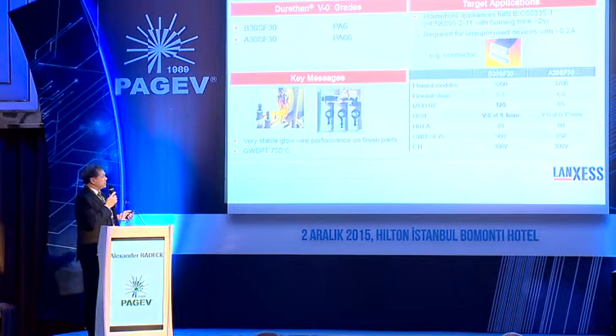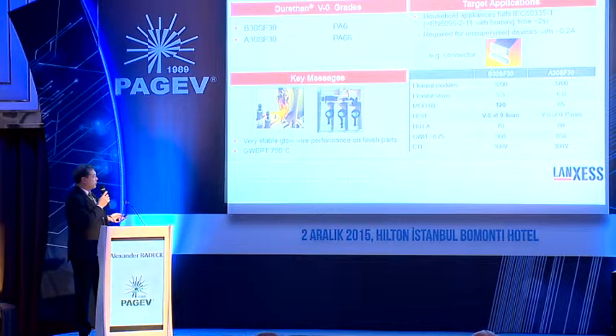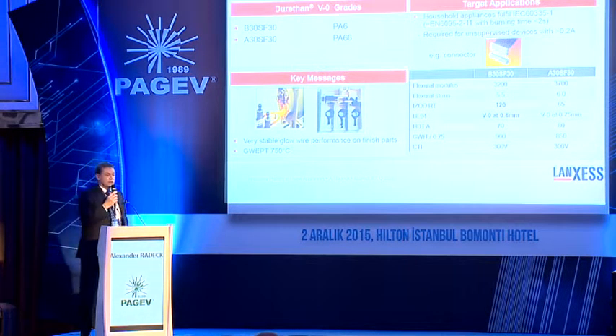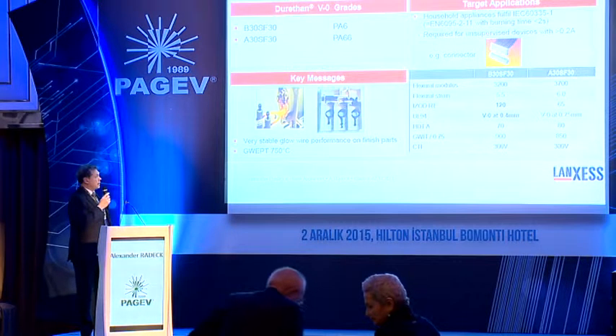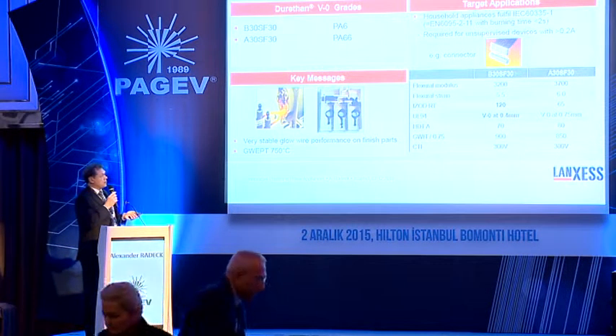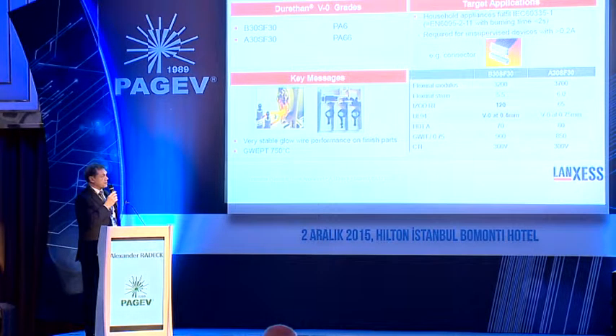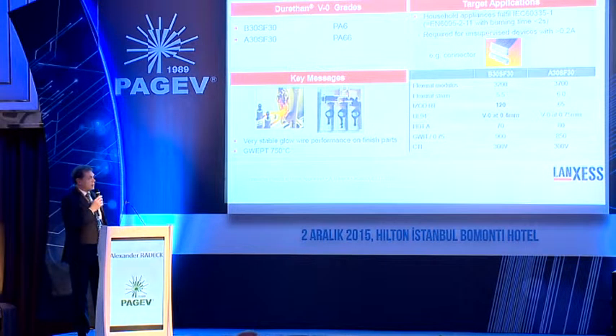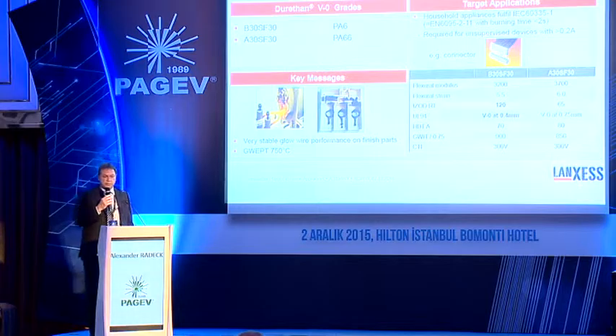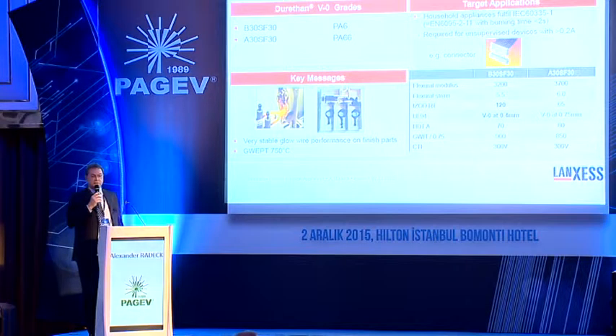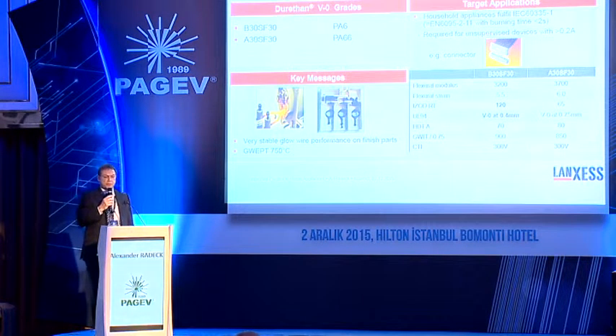And with this material development, you can do the glow wire test independent of the part design. You can do it wherever you want, and you have a very stable performance, and you reach at least 750 degrees Celsius. We have this in polyamide 6.6 as well as in polyamide 6, as you can see here in the right lower corner. Of course, polyamide 6.6 has some advantage in short-term heat resistance, whereas polyamide 6 has the advantage of a higher impact strength.